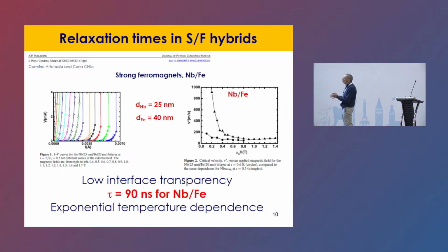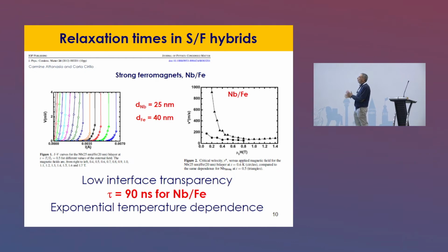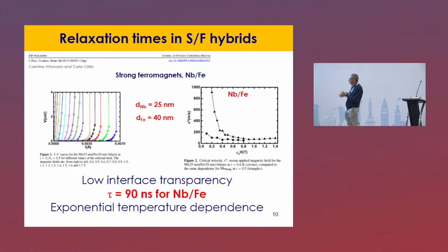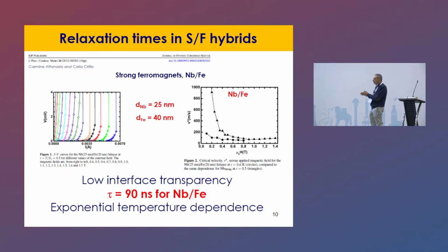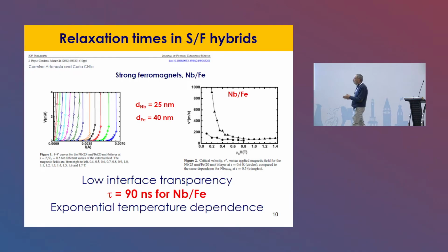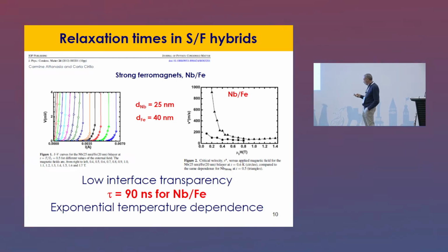Maybe this can be due to bad interface transparency between the two materials, or also to the fact that the penetration depth of the superconductivity in the iron is very, very low. So actually you always probe only niobium. In fact, also the temperature dependence of tau is exponential, and the feeling was that you were just measuring the properties of niobium.